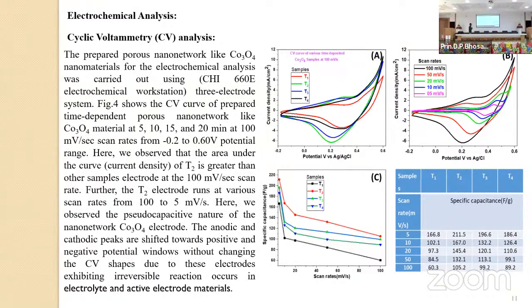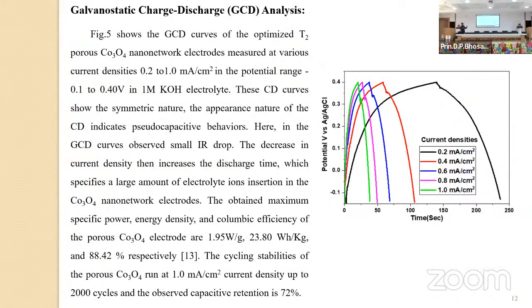Then the other CV curves, shown in figure B, are of the optimized sample, that is the 10-minute deposition time of cobalt oxide at various scan rates of 5 to 100 millivolt per second. Last, C is the graph of scan rate versus specific capacitance of the CV curves, and that shows the 10-minute deposition is a very promising cobalt oxide material, which shows 211.5 farad per gram. Here I can show it. Okay, next question, sir.